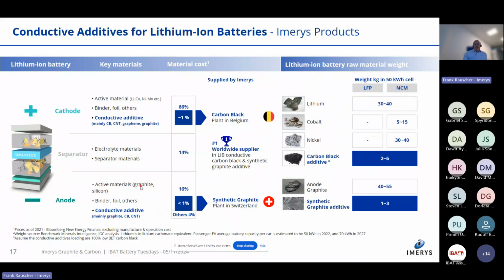And then on the anode, similar to what you see on the cathode, the active material here is graphite. It's a spheroidized graphite or a synthetic graphite that is very isotropic. Our material, again, is an anisotropic material. It doesn't work as active material, but it is an excellent conductive additive. Binder, conductive additive here, it's mainly our graphite, carbon black, but also CNT.